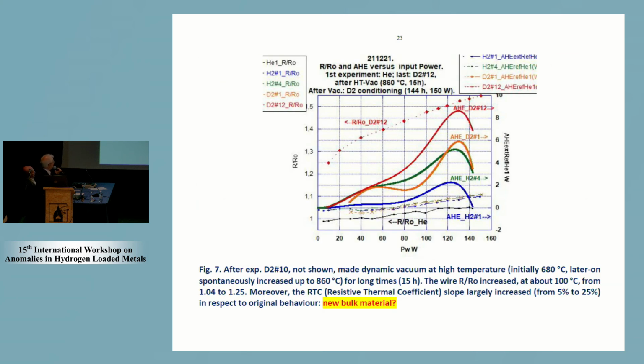So this is the resistance ratio for the pure constantan at the beginning. It's very, very stable. When we load some hydrogen, several cycles, or deuterium, there is some increase, but not so much, because it's counteracted by the effect of loading. But when before, for 15 hours, at very high temperature, we have a jump of the resistance ratio from about 1.04 to about 1.25, and moreover, a very large temperature coefficient. So it was the key to the understanding.